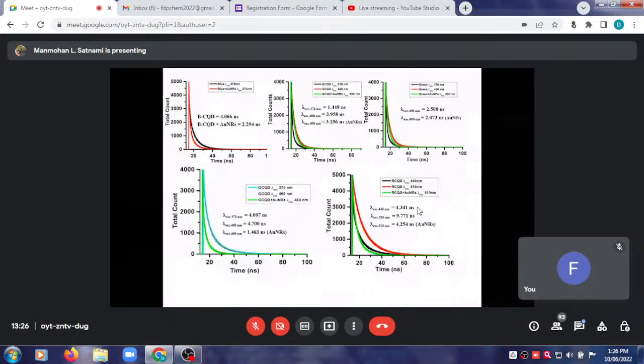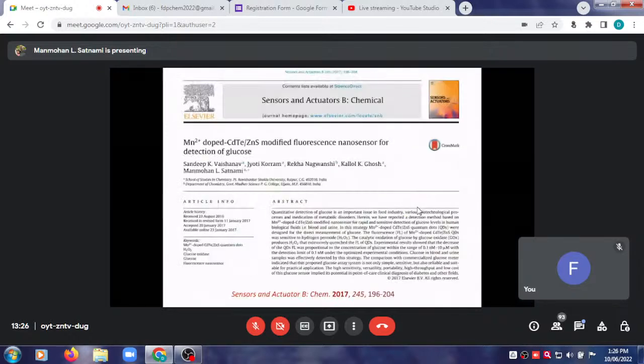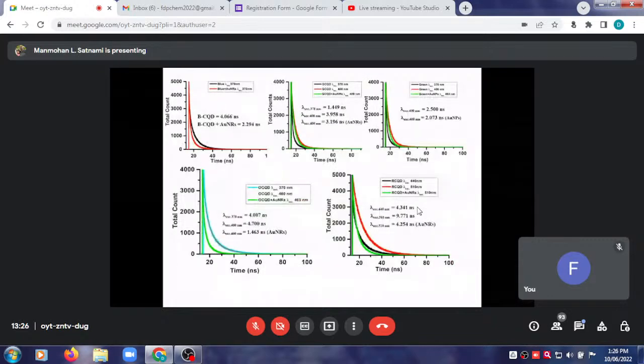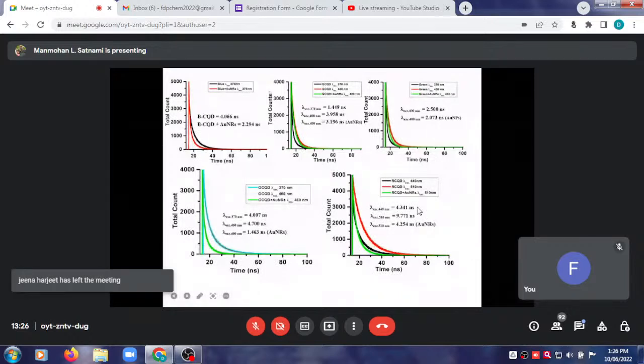So the work is actually going on. We have not yet reached the conclusion. Soon we will have more amount of data, and definitely we will have a good paper. And this is the lifetime measurement of carbon quantum dots. All the carbon quantum dots, blue, green, orange, and red, in the presence of gold nanorods. So from all these data, we can conclude that the lifetime of all the carbon quantum dots is decreasing in the presence of gold nanorods.